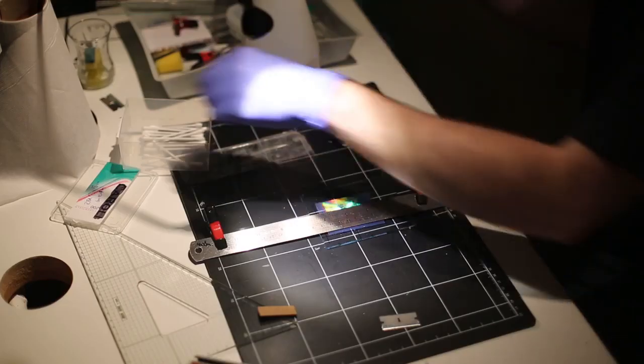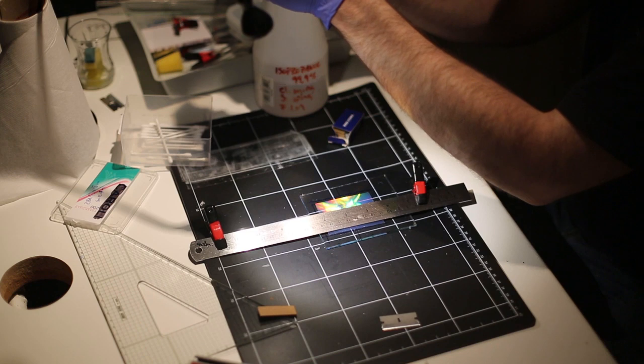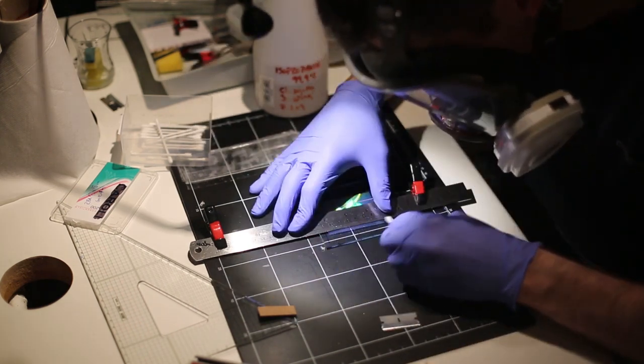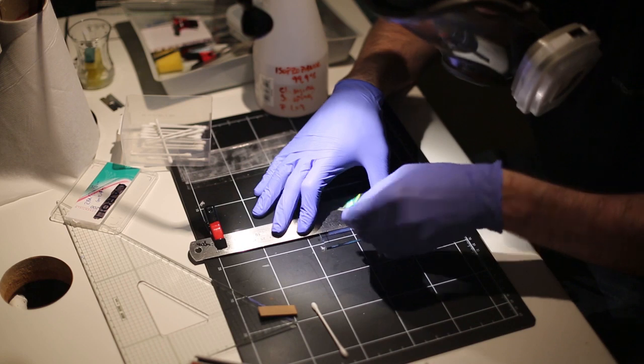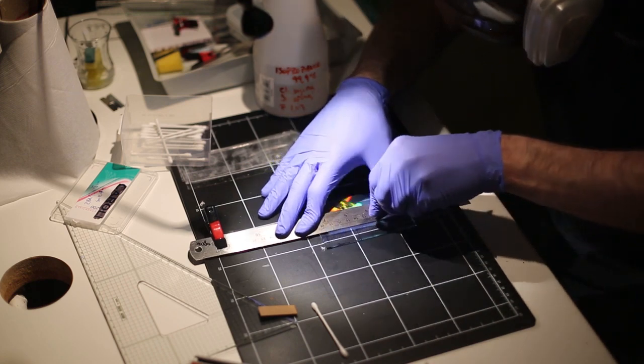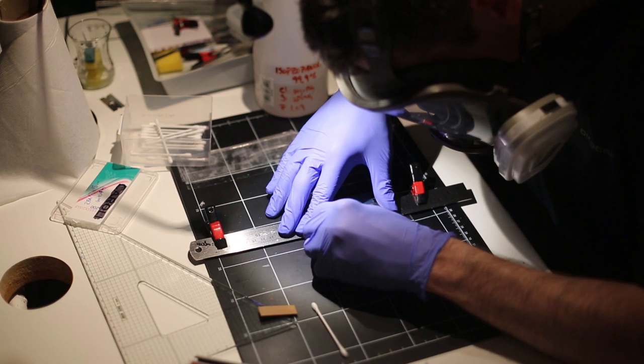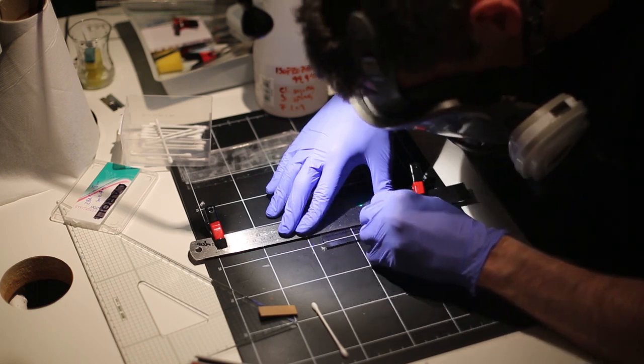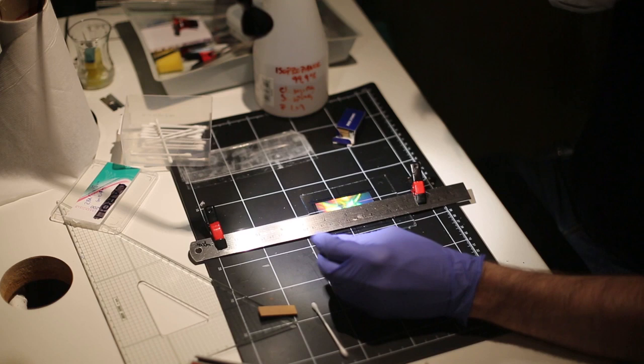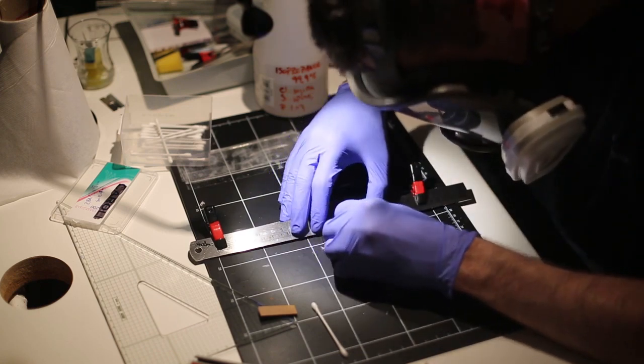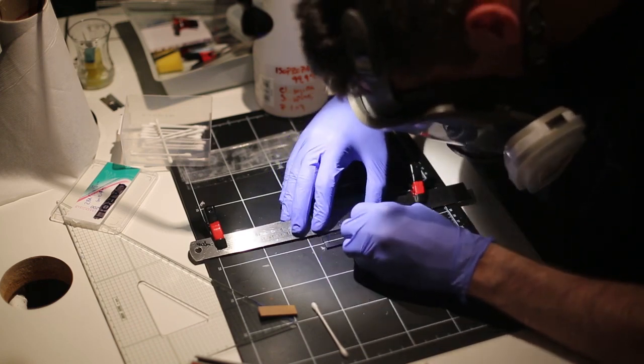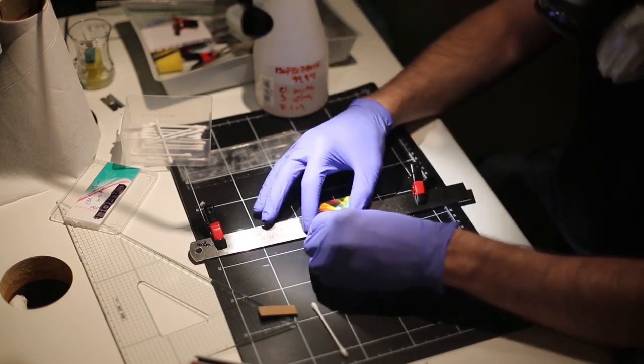I have attached 2 clamps to my steel ruler, so it's angled at 45 degrees. This way the ruler can't damage the emulsion by touching it. I take a cotton swab and spray it with 100% isopropyl alcohol and move it over the marked line. I place a ruler 0.5 millimeter next to this line and cut the emulsion with the pointy edge of a new razor blade. With the flat side of the same blade, I take off the emulsion. I repeat this process 4 times for every side.